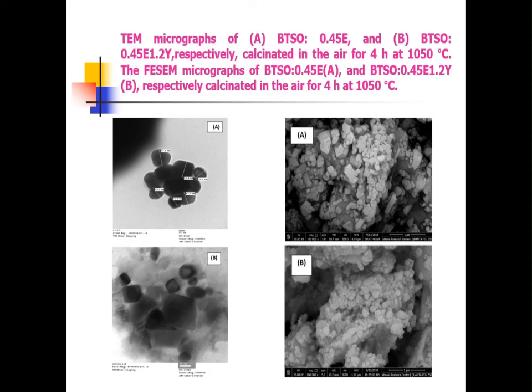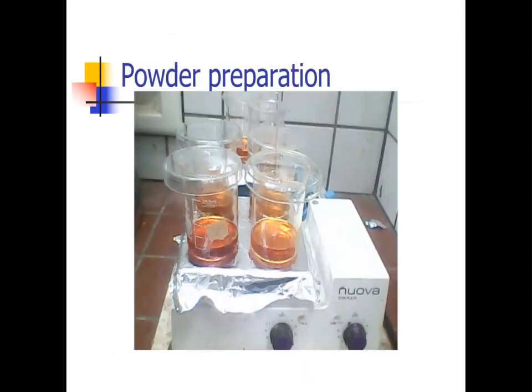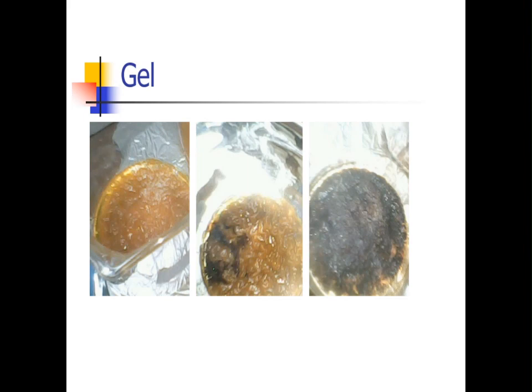The transmission electron microscope shows that the samples are in nanoscale, and here is the morphology detected on the right by the high-resolution field emission scanning electron microscope. Here are the steps of preparation of the barium titanate: in the solution case, then by heating it becomes a gel, and after that, drying at 350 degrees centigrade. After that we sinter it up to 1050 degrees centigrade to obtain a single phase of barium titanate and barium titanate doped with Sn. It gives us a very clear powder.